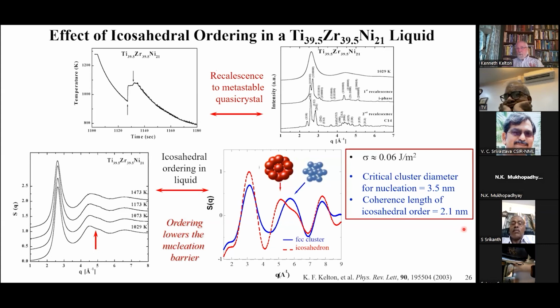So what this says to me, coupled with the low interfacial free energy, is that the icosahedral ordering in the liquid has lowered the nucleation barrier for forming the I phase. But the fact that you have a length scale where it starts to nucleate says that within this liquid, you have certain regions of icosahedral order. And then that raises the question, is that homogeneous or heterogeneous? Because you've got certain sites in the liquid that are catalyzing the formation of the phase. And I would argue that that's blurring the distinction between homogeneous and heterogeneous.